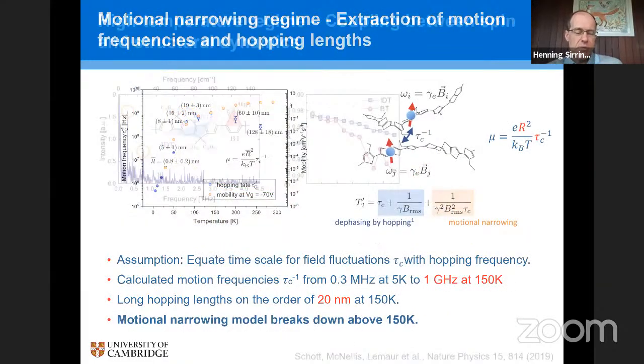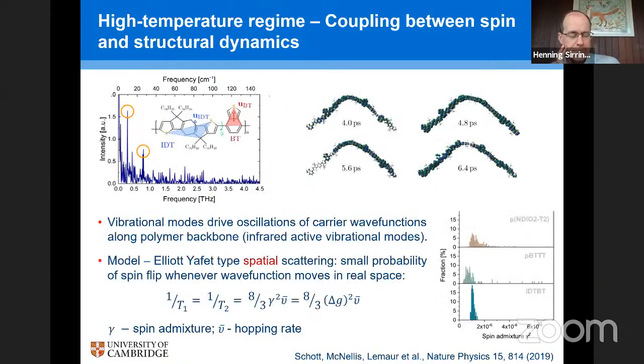And it turns out that the reason why the spin relaxation time goes down again towards room temperature is because the spins start to couple very strongly to the structural dynamics. As you go towards room temperature, also in a polymeric system, you have these large vibrational motions, and in particular you have to think about the torsional vibrations of the ring systems in the polymer chain against each other. So there are thermally excited torsional vibrations. And what these do is something very similar to what's happening in the molecular systems I explained at the beginning.